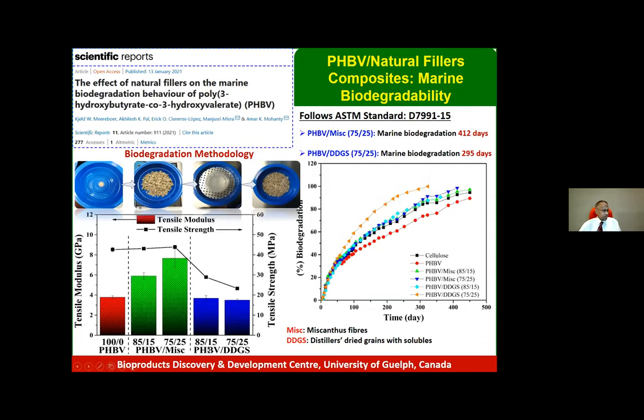Here, 85% and 15% of DDGS, distillers dried grains with solubles. So what I want to say here is your modulus goes up and strength decreases a little, but surprisingly, we use miscanthus fiber as a filler in the bioplastic. We use distillers dried grains as a filler in the bioplastic, but the overall idea is here. If you use 25% natural fiber in this plastic, the marine biodegradation happens in 412 days. If you use distillers dried grains, marine degradation happens in 295 days.